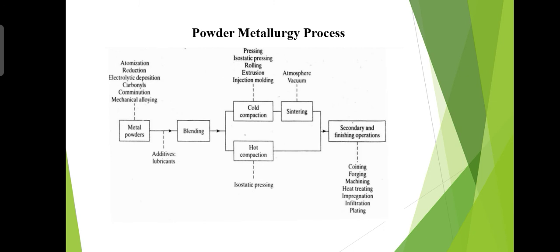For metals that become brittle at low temperature, to break them and produce their powder, the milling operation, cryogenic milling, is used, for example in the manufacturing of molybdenum powders. This method is also known as the cold stream process. Here bulk material is cooled with liquid nitrogen and projected into two opposite streams to a crossover point, and in these two streams the material is broken down, and the process continues until the desired size distribution is obtained. So this is a basic method of producing metal powders.